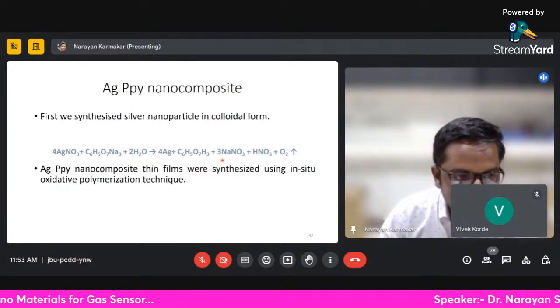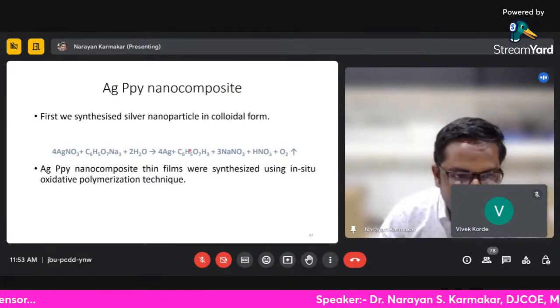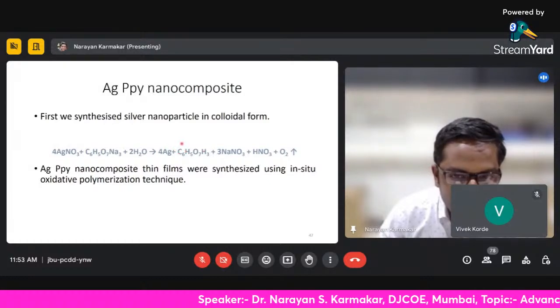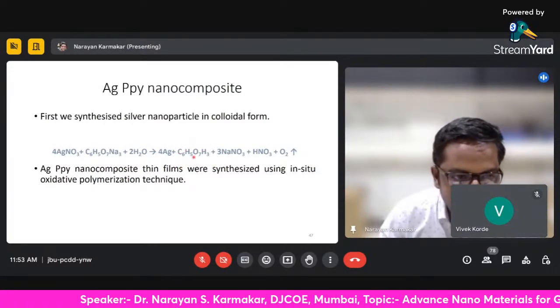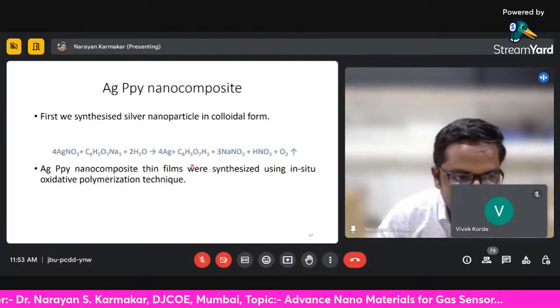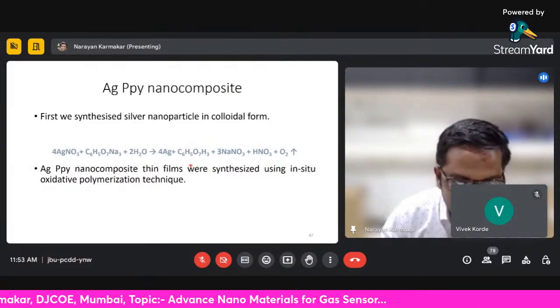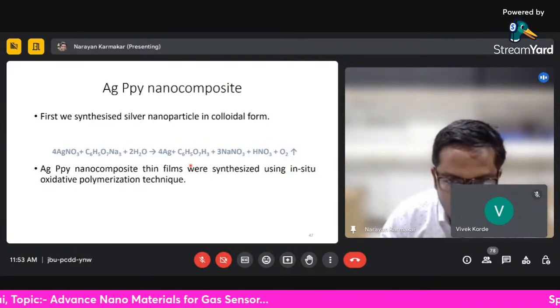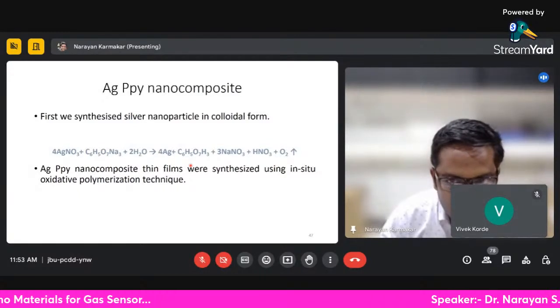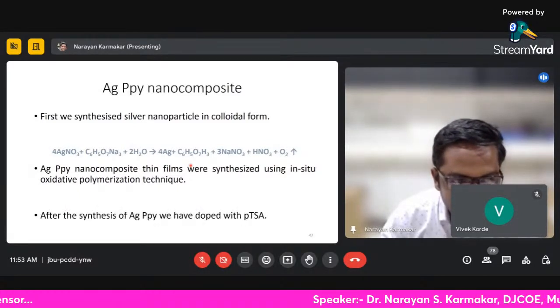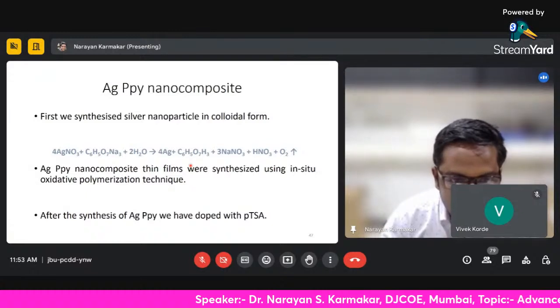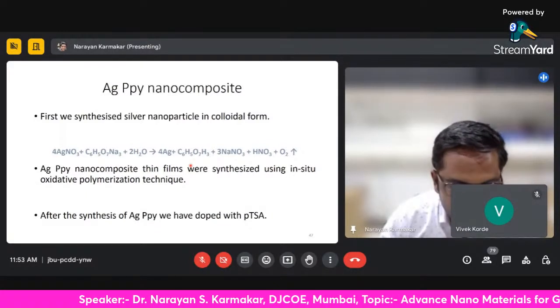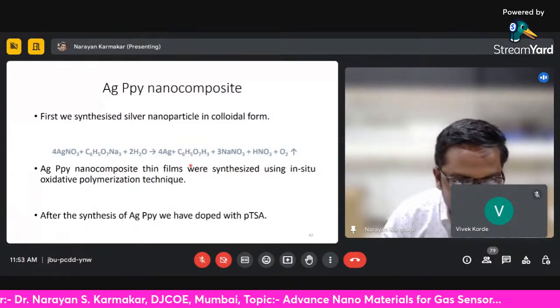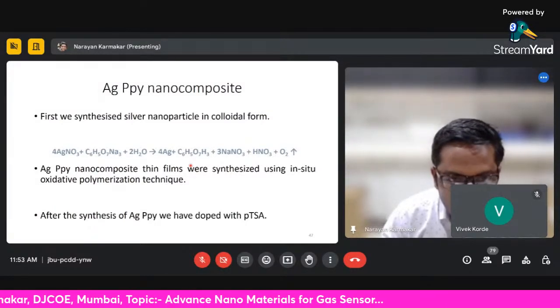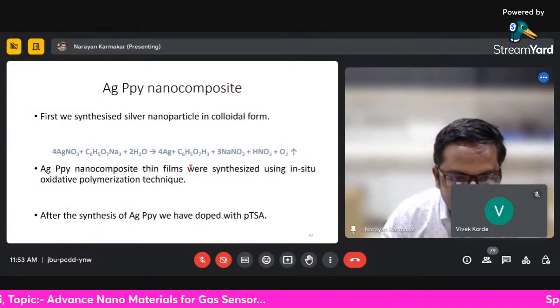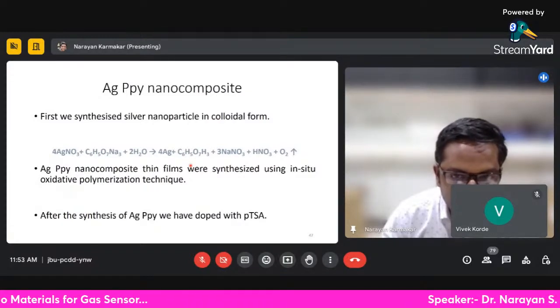To that, we added pyrrole. Because of this citrate ion, polymerization happens surrounding the silver nanoparticle. After the synthesis of this AgPPy nanocomposite, we dope it with PTSA. So this is the procedure we followed for synthesis of the silver nanoparticle polypyrrole doped with PTSA.